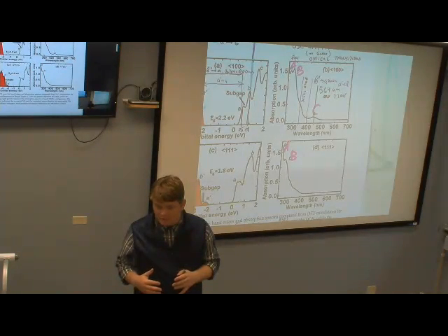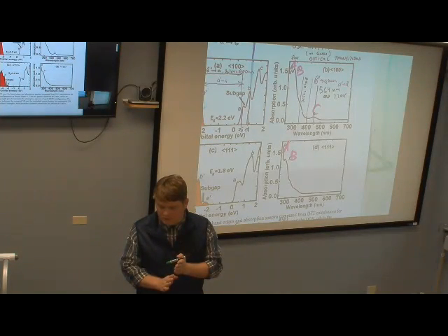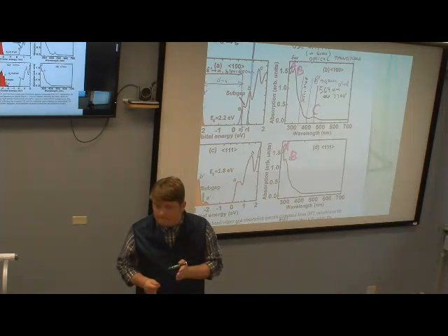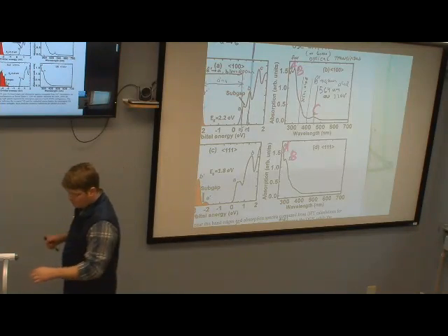And maybe here in nanowires, it's not as important, but maybe it's just heavily degenerate, or it is because of indirect band gap features. Some bands have their minimum not at the gamma point but aside, and this may spoil expectations. But a reviewer will likely ask a question about Van Hove.